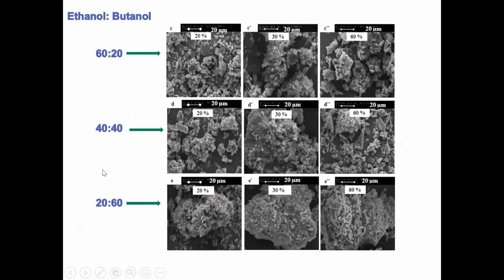And if you use binary mixtures of these two solvents rather than a pure one, you can actually tune the surface of lactose particles. And you will see that some of them can give you actually nano surfaces like this one or this one. If you magnify, these are right around maybe 500 nanometers, and we call them nano surfaces.